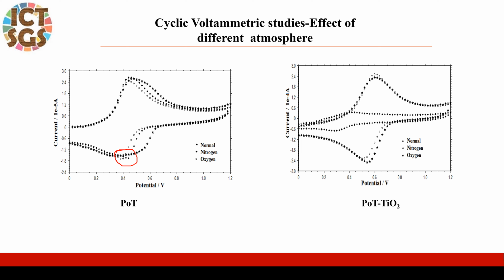In the case of PoT-TiO2, the current density corresponding to the redox peaks is significantly higher at low potential, and the reduction peak shifted towards more negative potential, which indicates enhancement in the ORR activity.